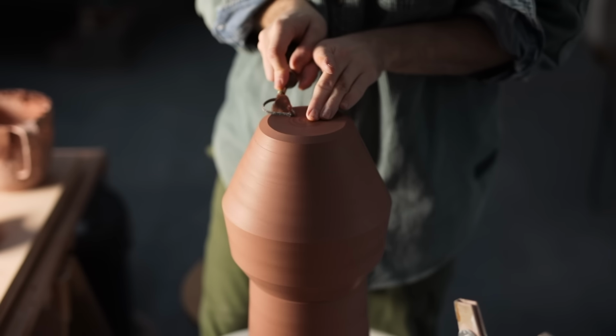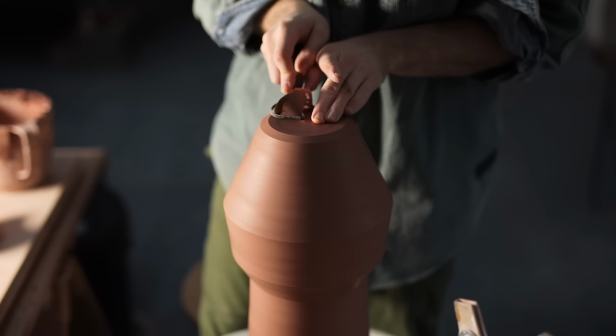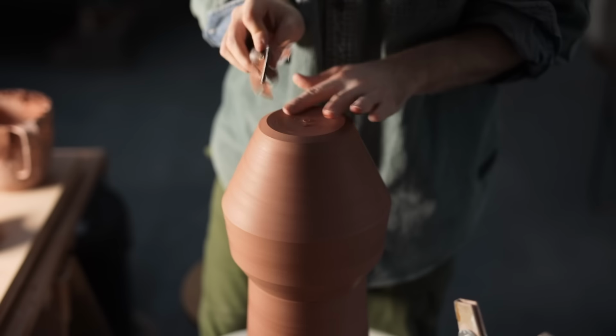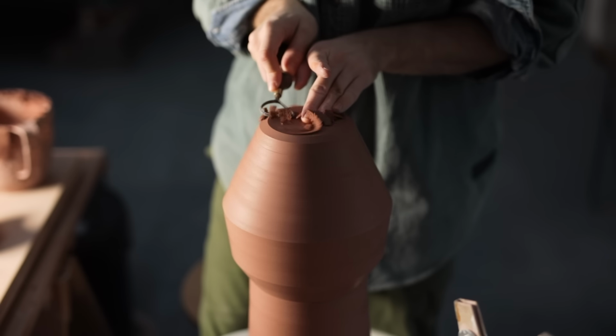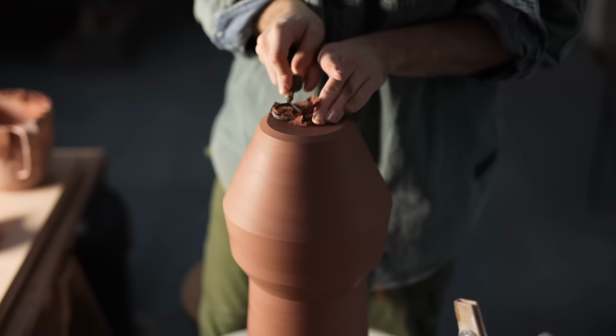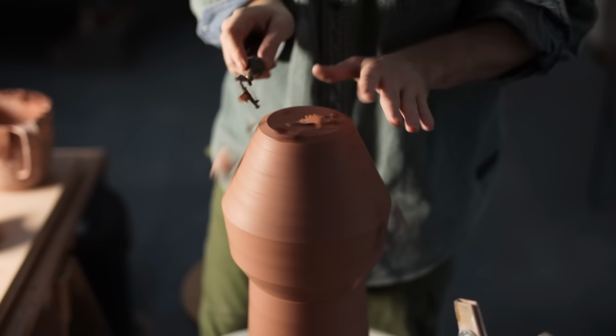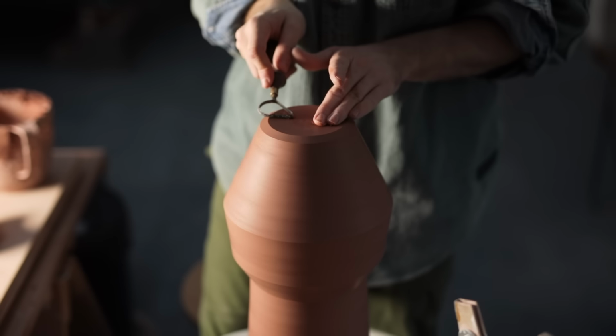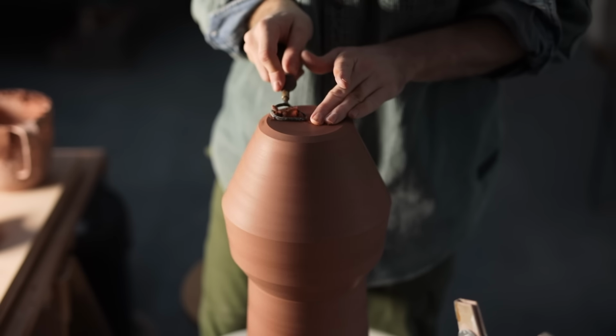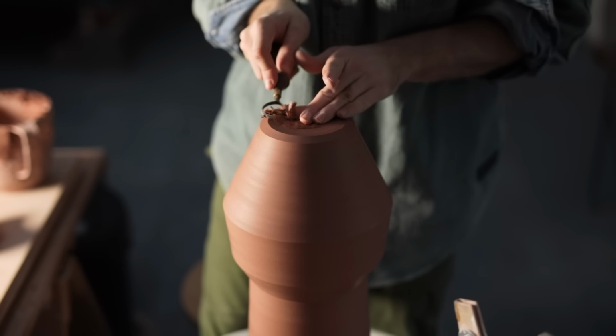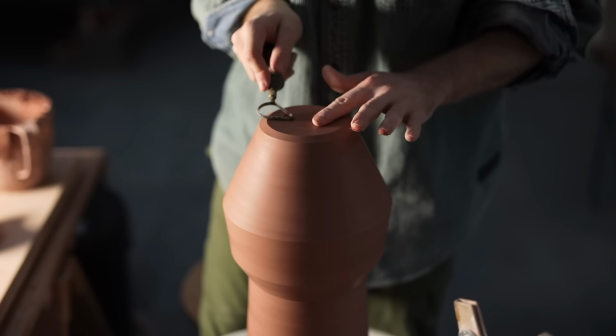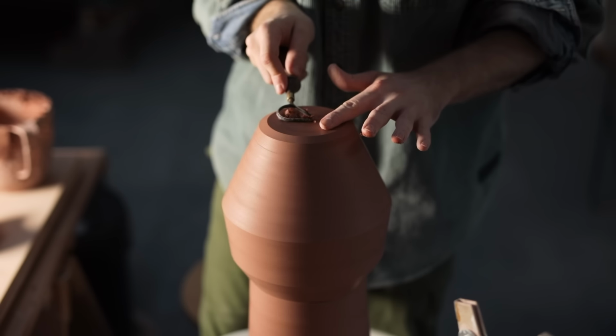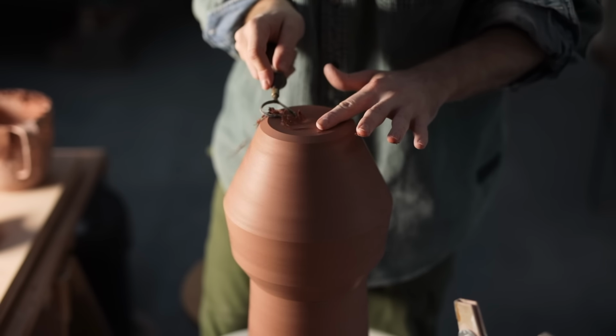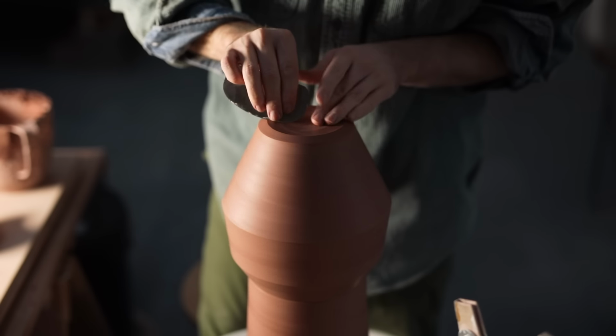I trim away the wiring off marks which are left over from when the pot is removed from the wheelhead. I also very slightly bevel the outer edge. This removes what would be quite a sharp angle which could very likely chip once fired when the pot's moved around and put in place. High iron stoneware clay bodies tend to be quite brittle, especially when they're trimmed thinly and reduction fired, so just softening that bottom corner does make a big difference, as it's very likely the part of the pot that'll be knocked around the most.